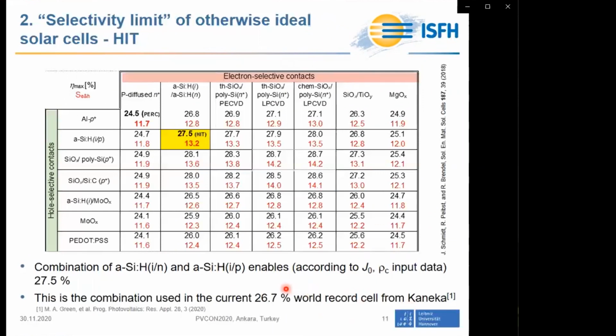Another very promising combination of electron and hole collecting contacts is the combination of an N-type doped amorphous silicon layer on an intrinsic layer with a P-type doped amorphous silicon layer, also on an intrinsic layer. This combination can reach, according to our input data, a combined selectivity of 13.2 and a selectivity limit of 27.5%. It is used, for example, in the current world record cell for crystalline silicon single junctions from Kaneka, which reaches an efficiency of 26.7%. So it's rather consistent with our simplified consideration.